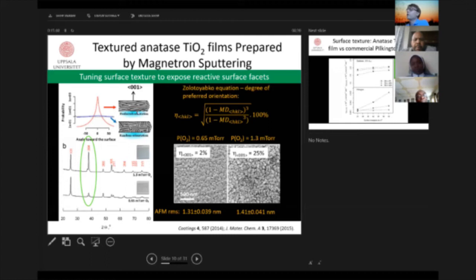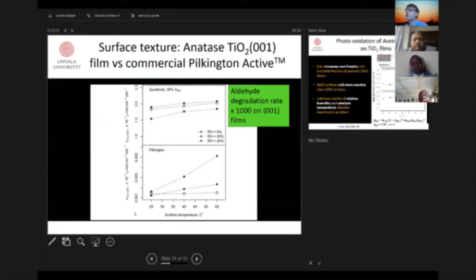Knowing this, you can tune how the surface is terminated, that is, how the exposed surface facets look. And knowing what I said before, that you can use this to moderate the bonding of key intermediates, you can use this technology to improve the sustained activity, not the initial activity, but the sustained. This picture shows an example of how we have oriented the films. So 36% of the surface is oriented with the 001 orientation. And look at the y-axis scale, compared to a commercial film. That is 1,000 times more effective in terms of rate in absolute numbers compared to commercial films, which have nanostructures and are absolutely not optimized for these conditions.